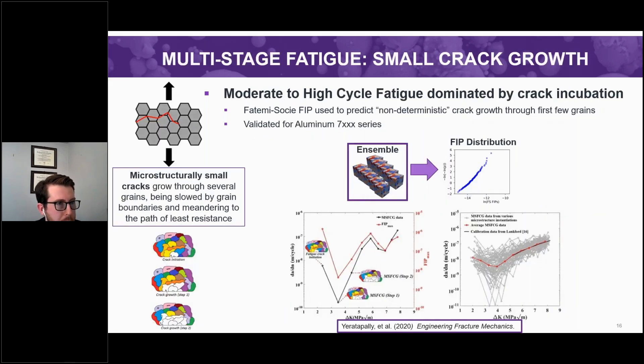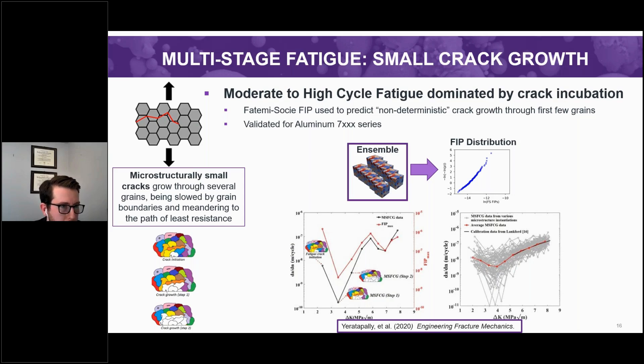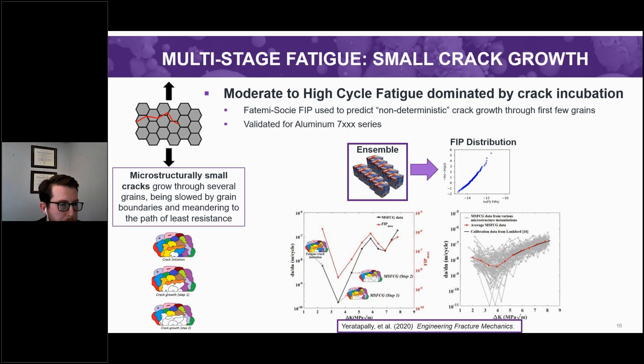Next, we model microstructurally small crack growth using a similar approach. Instead of looking at the highest fatigue indicator parameter in our microstructure, we care about all of the fatigue indicator parameters in the neighborhood. We simulate ensembles of statistical volume elements and characterize extreme value distributions of those fatigue indicator parameters. We then use a non-deterministic approach to fatigue crack growth, where we simulate the crack growing outward from the initial grain in all directions — growing from the first grain to the second nearest neighbors and then the third nearest neighbors in three dimensions. By simulating all of these different paths, we can determine the path of least resistance to determine the minimum fatigue life.